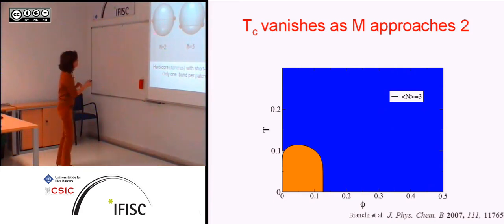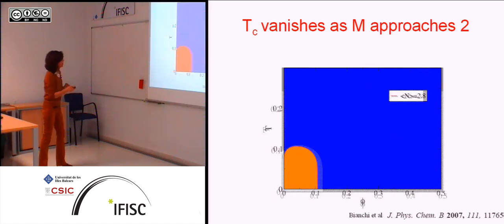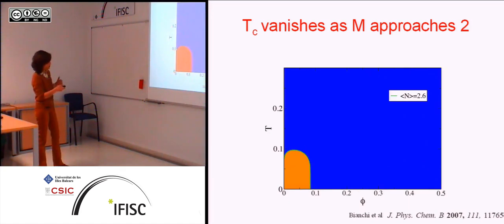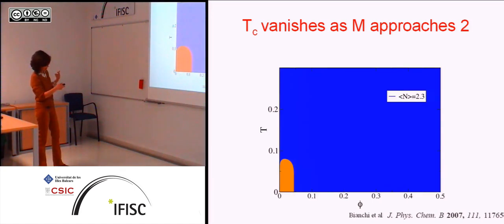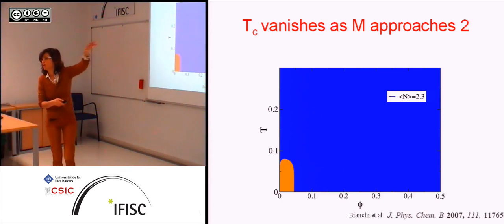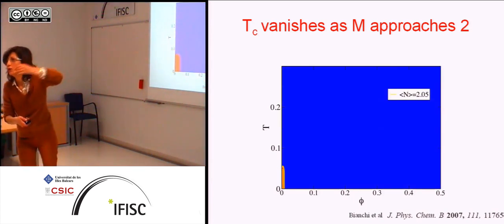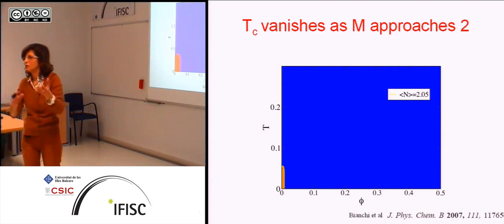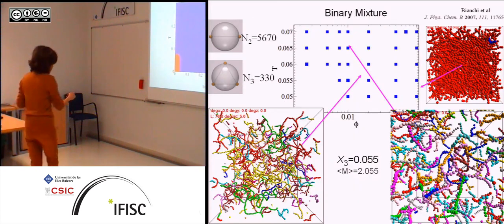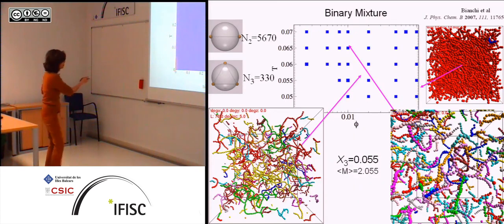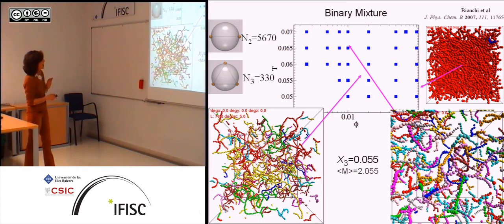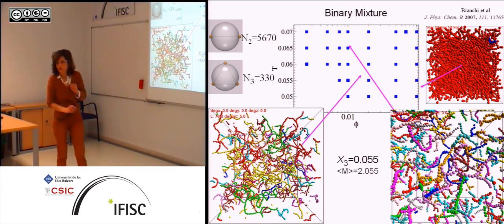So the interesting range is really in between, and in fact, they've shown through theory and simulations that they can decrease the critical temperature by decreasing the average number of spots. How did they manage to have a number of spots which is less than 3 or which is non-integer? They did a mixture of colloids with 2 and 3 spots. And so you can go to 0 as this number approaches 2, okay? So you see, this is kind of known, and this is the structure of those systems.